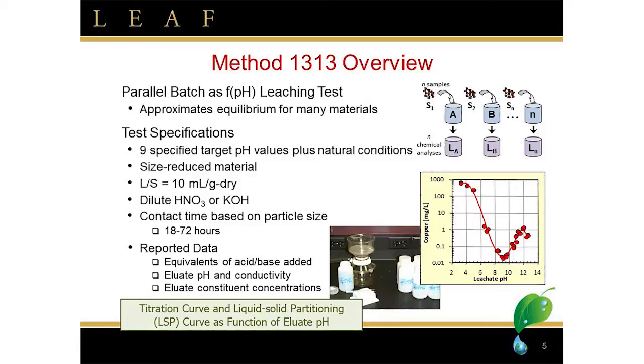The method itself is specified for 9 target pH values plus the natural pH condition, and it's on size-reduced material, with a liquid to solid ratio of 10 milliliters per gram dry weight. You use either dilute nitric acid or potassium hydroxide to adjust the pH to the final target endpoint pH. Then you have contact times between 18 and 72 hours based on particle size. It gives you an outcome of a titration curve, eluate pH and conductivity, and eluate concentrations. Importantly, it gives you a characteristic curve that shows you what the leaching behavior is as a function of pH, which allows you to interpolate or extrapolate to different conditions that may be out in the field or different pH conditions.